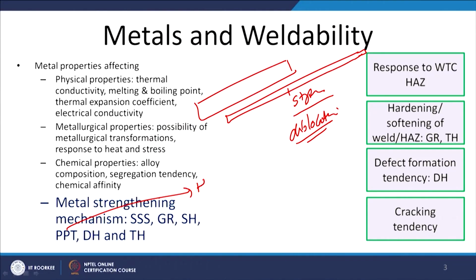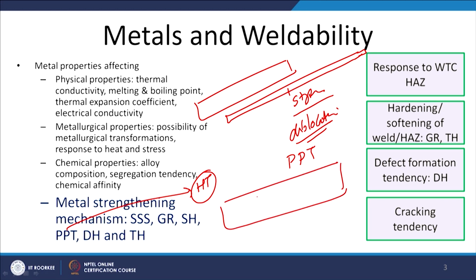Then there is the heat treatment based approach of strengthening, which is called precipitation hardening. In this case, very fine, well distributed precipitates of the suitable type are developed in the metal through a controlled heat treatment cycle of solutionizing, quenching and aging, which may be natural aging or artificial aging, and this leads to the formation of the required precipitates for realizing the desired strength.